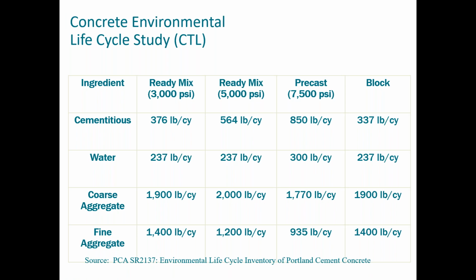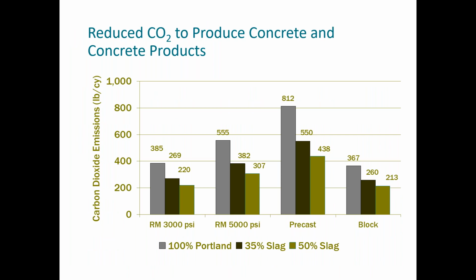One of the things that we also see is that it's not only the ready mix industry; precast, masonry block, and other concrete materials can use slag. In this case, this was a study that was done by the PCA using CTL. As we can see, there are different cementitious amounts, water, coarse aggregate, and fine aggregate. But if we go on to the next slide, we will see that in every case, when we went from 100% Portland to 35% slag replacement, or even 50% slag replacement, we are going to see the CO2 reduction in the materials. Next slide.